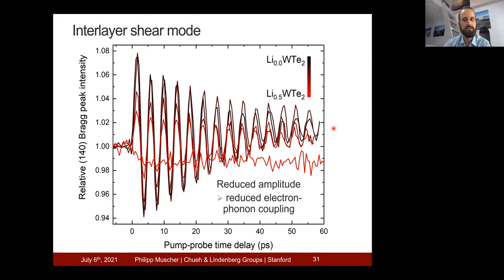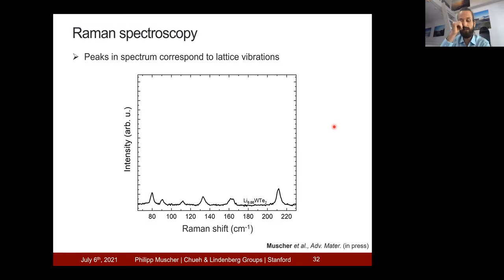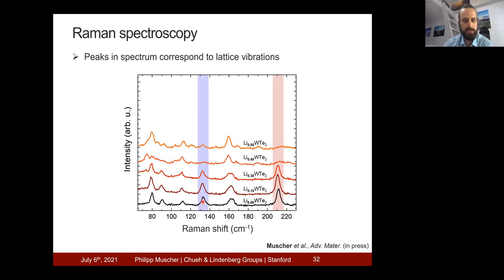However, we can use another technique to look at multiple vibrations at a time, without the specific atomistic details. This technique is called Raman spectroscopy. In this Raman spectrum, each peak corresponds to a lattice vibration. Here the Raman spectrum is shown for tungsten ditelluride with no lithium inserted. How does that spectrum evolve with lithiation? For this, I want to turn your attention to two particular peaks. You can see that with lithiation, both of these peaks are disappearing. So we see a vastly changed Raman spectrum due to lithium insertion.